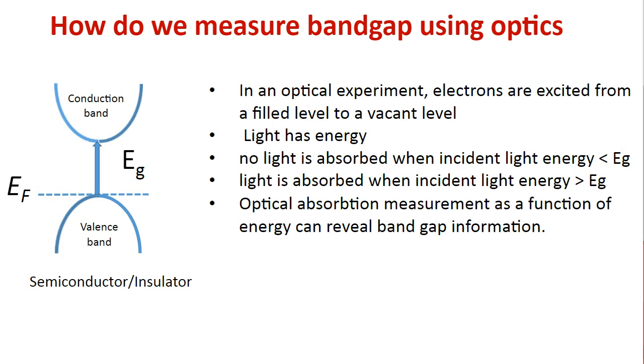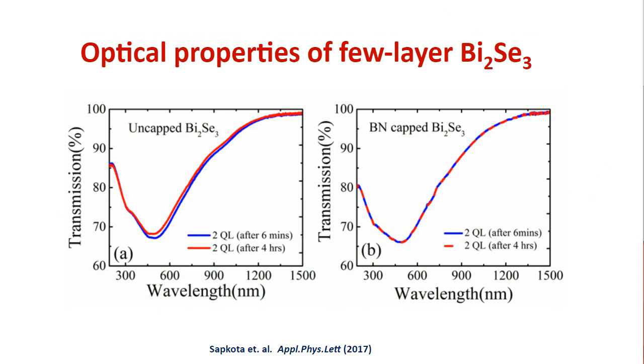So the first thing that we did was to measure the transmission of several bismuth selenide thin films. These were also fabricated using the magnetron sputtering method that I was talking about earlier. So I'm not going to go into details. It's very similar to MoS2. We take a composite target, we sputter, anneal the sample, and look at the optical absorption.